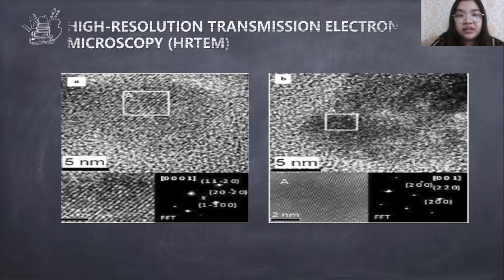related to hexagonal quartz with lattice parameters of 0.343 nanometers, 0.243 nanometers, and 0.198 nanometers. For sugarcane bagasse, it has tetragonal arrangement lattice parameters of 0.2 nanometers, 0.199 nanometers, and 0.142 nanometers. With the result of these two, we concluded that the vermicompost has an important role for silica oxide nanoparticles to have crystalline phases.